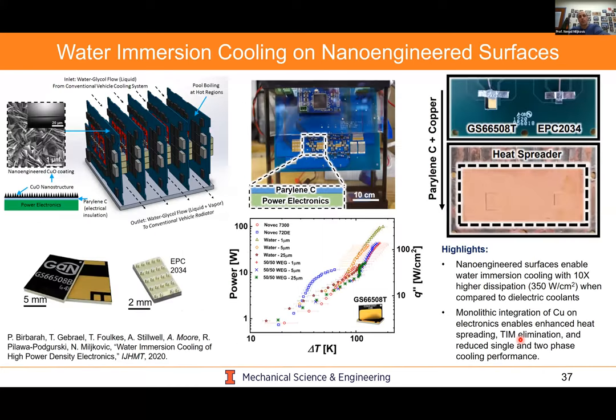We're also excited by recent work and progress on metallization of electronics. This is actually spin-off work from an initial study, which we did 3-4 years ago, looking at how we could create immersion cooling in water or dipping our electronics directly in water using hydrophobic polymer coating. What you're actually seeing here, and please don't call me crazy, you're looking at a PCB board with two different gallium nitride devices mounted on it that's actually been coated with copper. This is actually copper right on top of your electronics.